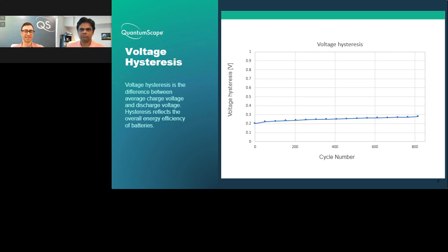Well, this voltage hysteresis represents losses in the battery. It represents inefficiency of the battery. So the larger the hysteresis is, the more inefficiency the battery has as it cycles. And that means there's wasted energy on the grid and there's excess power that is dumped as heat into the battery. And so then the battery would need some active cooling potentially to avoid it from getting too hot if there are large inefficiencies. So what this chart is showing is that at a 1C rate, which is, like Venkat said, basically a supercharger charge rate, 1C rate of charge and discharge, the voltage hysteresis is still modest and relatively stable throughout cycling.